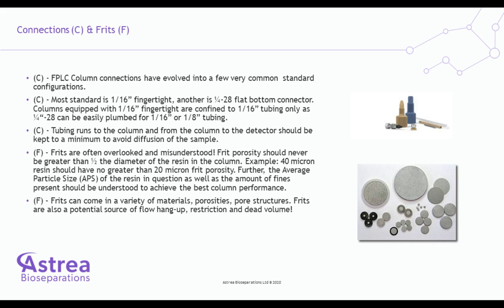So if we pick a frit that has too large a pore size, assuming that everything's 40, our fines and smaller particles are going to jam those frits up. We're going to have flow restrictions, and we're going to have complications with our chromatography. Conversely, if we want to take the more conservative route and go with a very fine pore size in our frits, we will find that we have a much higher back pressure, and we have that obstacle to deal with. So we would talk to our customers when people come to us and find out a little bit more information about what resin you're using in your columns, what flow rate you're expecting.